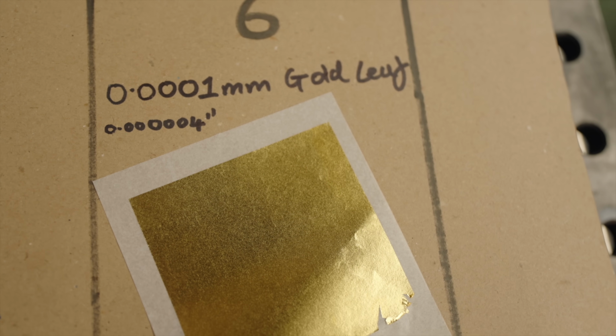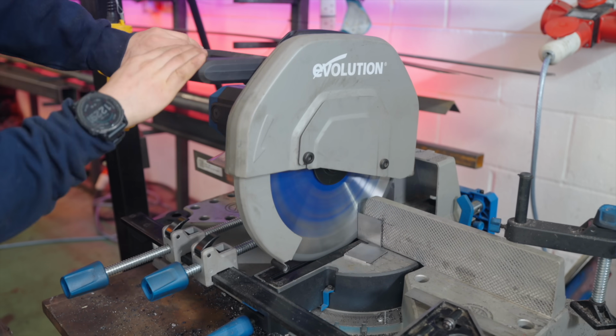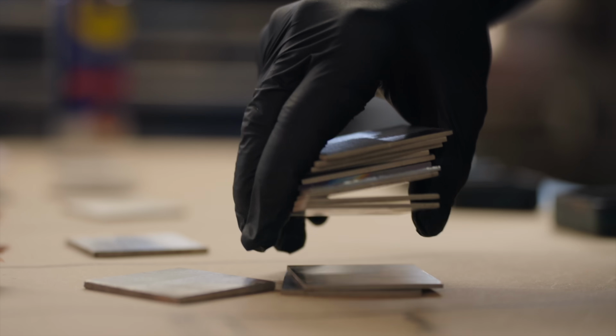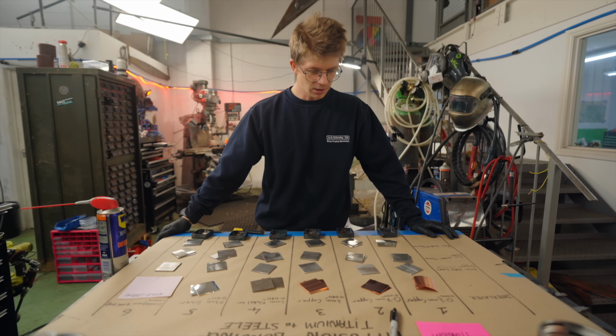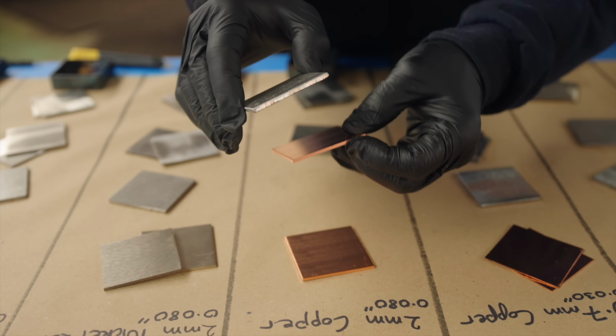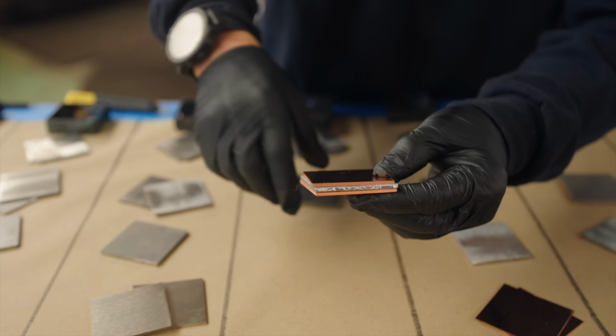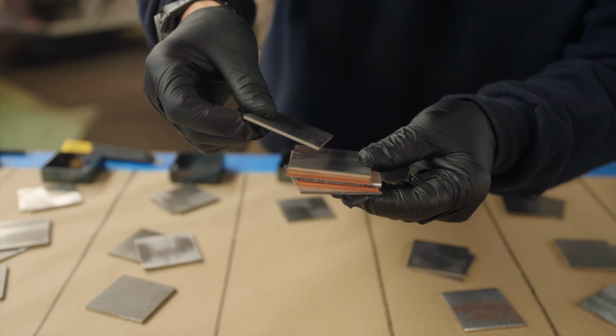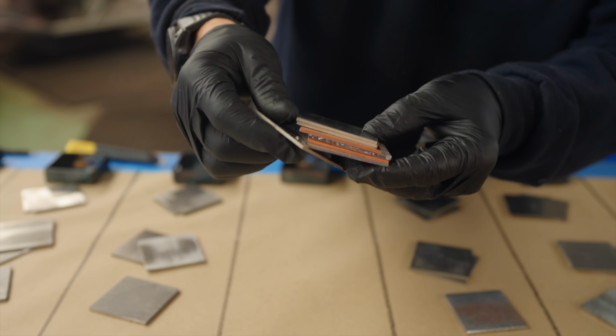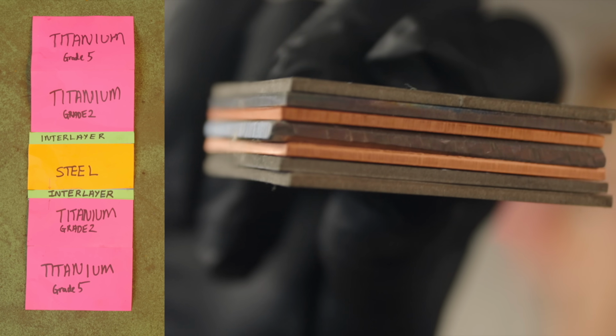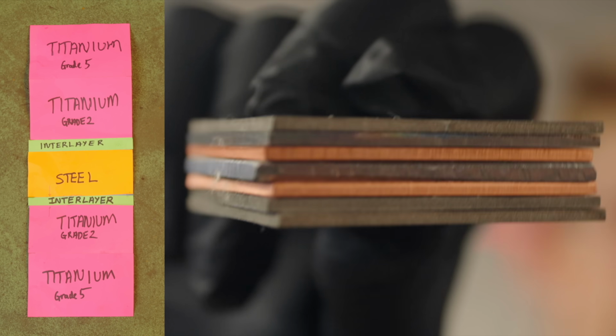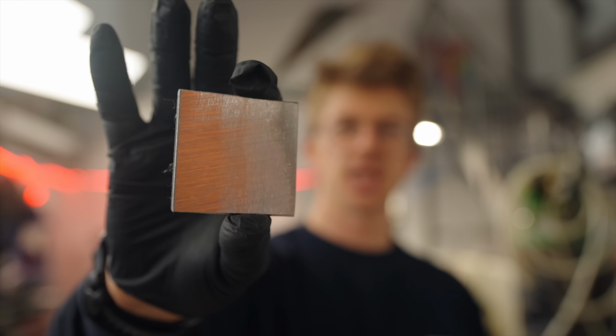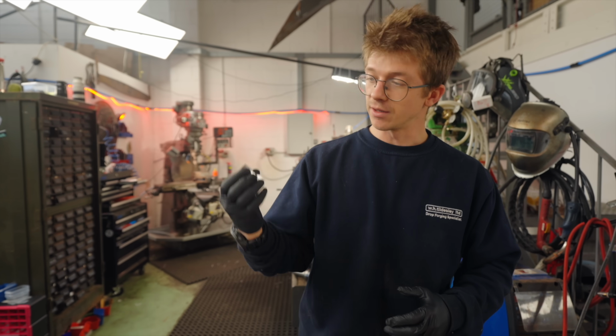That is very thin. Now going to cut our 1080 steel. This is a lot of stuff. Our sandwich: steel in the middle, interlayer either side, grade 2 titanium either side of it, and just for fun, grade 5 on the outside. That is going to be our forbidden sandwich. But I'd really like to have more consistent surface finishes, especially on the steel, because it comes from the mill a lot rougher than the titanium did.